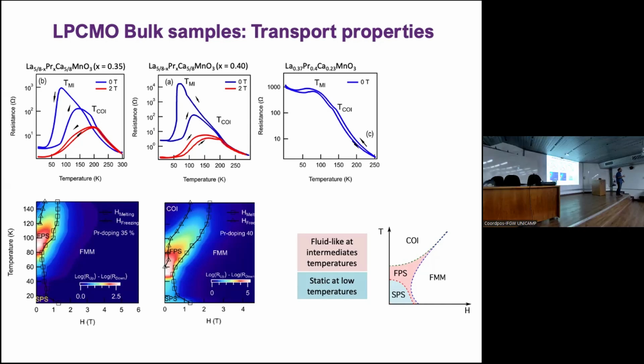So instead of doping, you can actually just change the strain. One thing that I have in mind, and I did that with vanadium oxide, is that you can grow the manganite on a piezoelectric substrate and then just put voltage into the substrate, and you will somehow mimic the same strain profile as with the doping. In the case of vanadium oxide, it works beautifully. You can change the transition temperature by a lot.